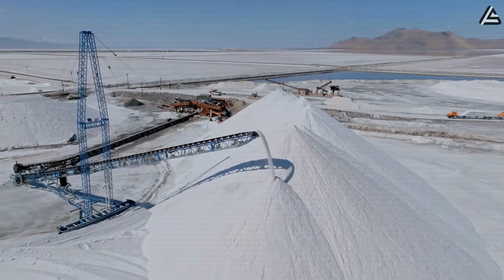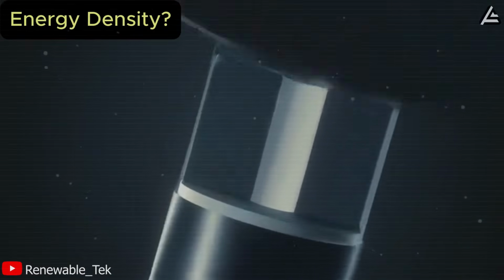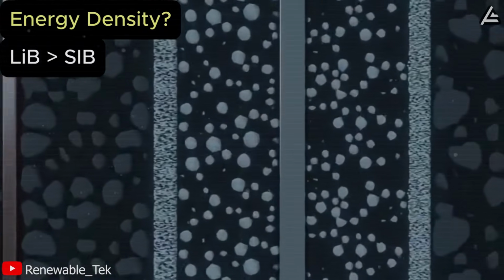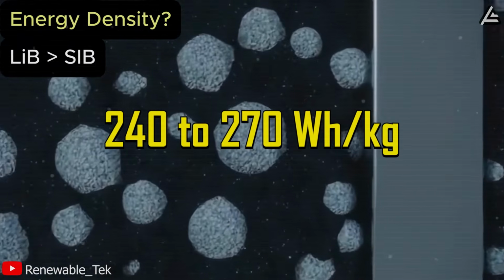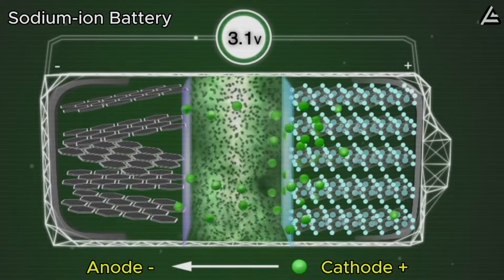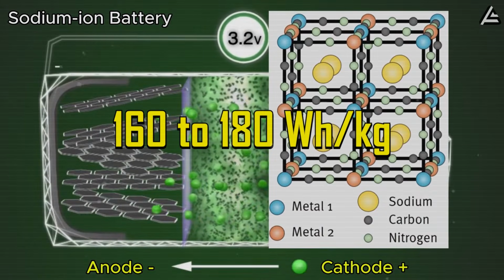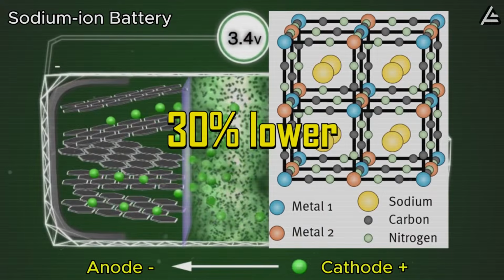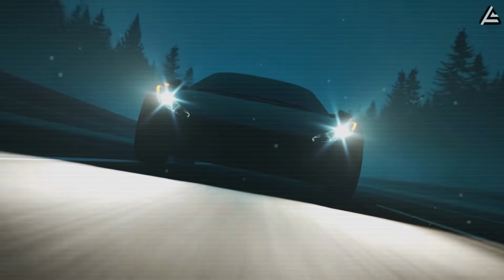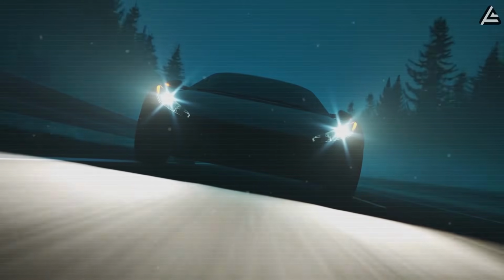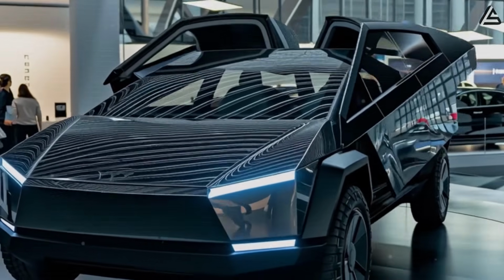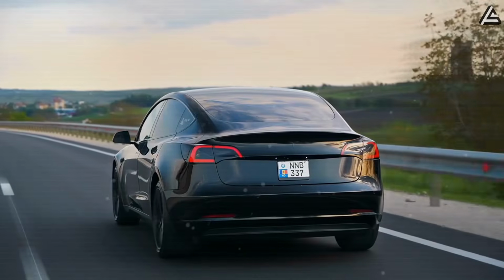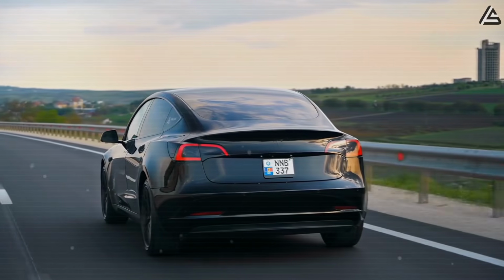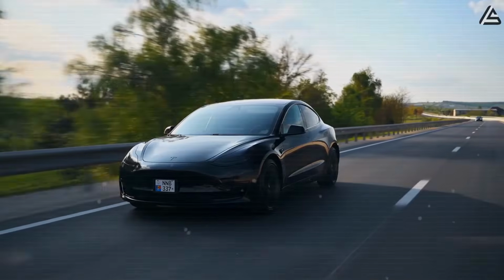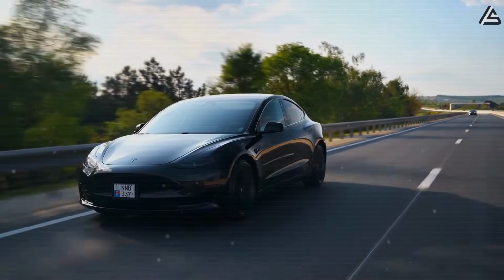In terms of technical performance, lithium-ion still dominates on raw energy density, typically delivering 240 to 270 watt-hours per kilogram at the cell level. Sodium-ion, in contrast, achieves around 160 to 180 watt-hours per kilogram, roughly 30% lower. However, Tesla appears to be betting that absolute range isn't everything, especially for a budget-friendly EV like the Model 2. Most daily drivers rarely need more than 200 to 300 kilometers per charge. And for that range, sodium-ion is more than sufficient.